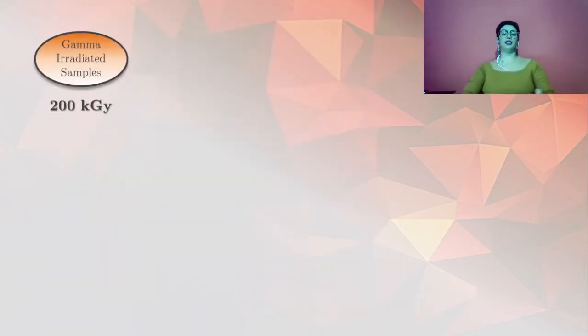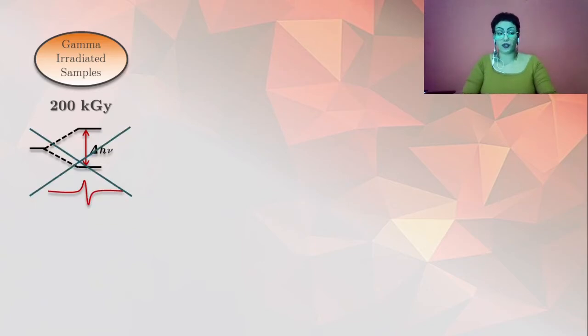The gamma-irradiated batch of samples was prepared from each mother sample and submitted to a 200 kGy dose of gamma radiation in order to ionize possible existing defects in the mother samples and increase the concentration of the paramagnetic centers. However, no spin resonance transitions were observed.